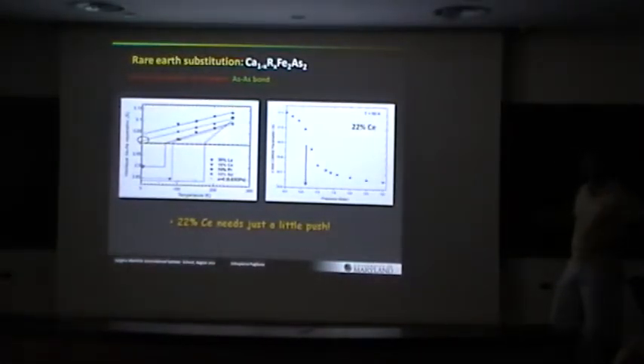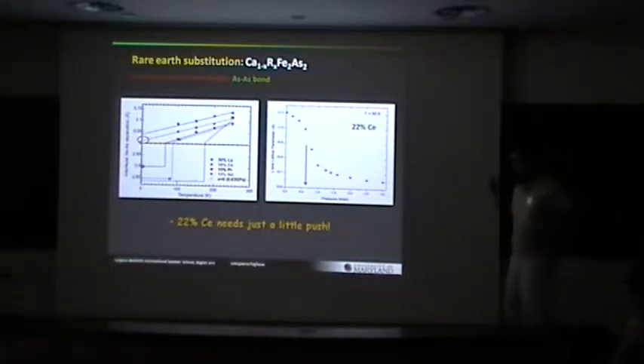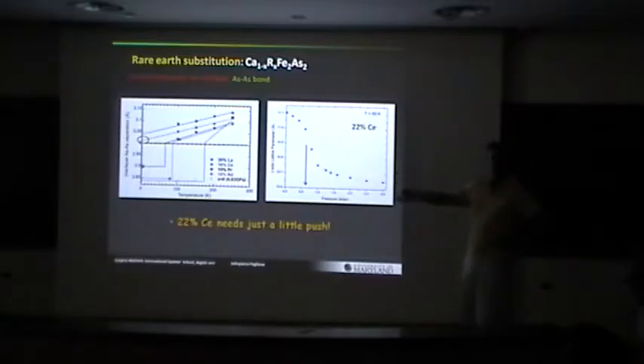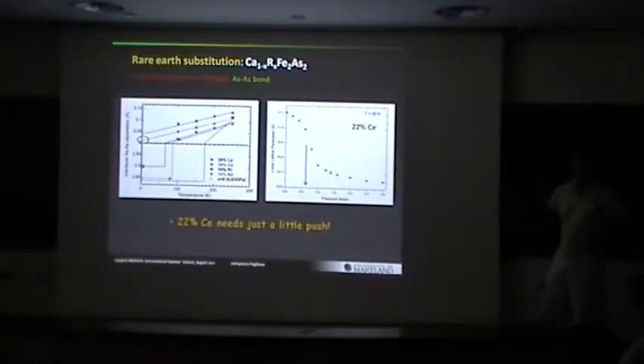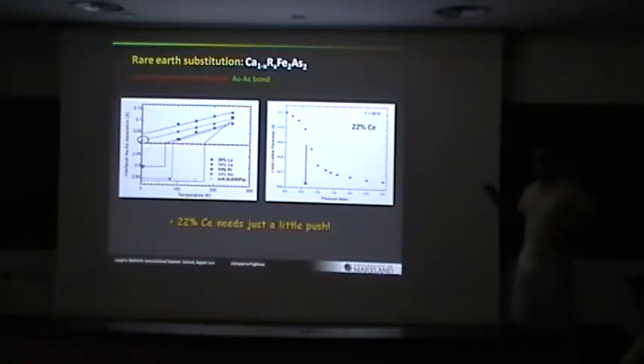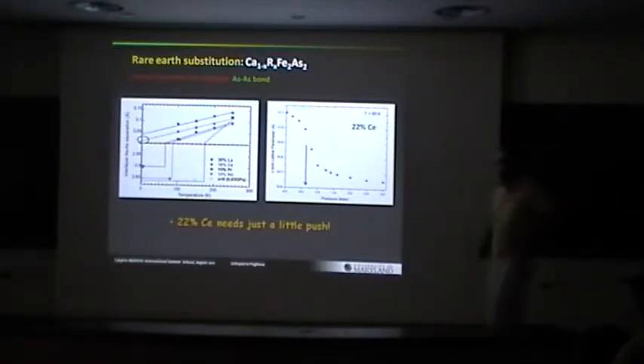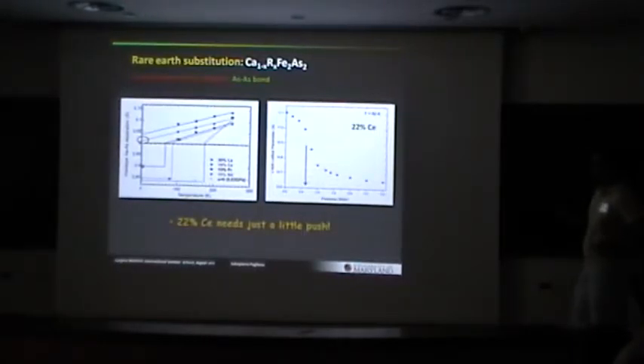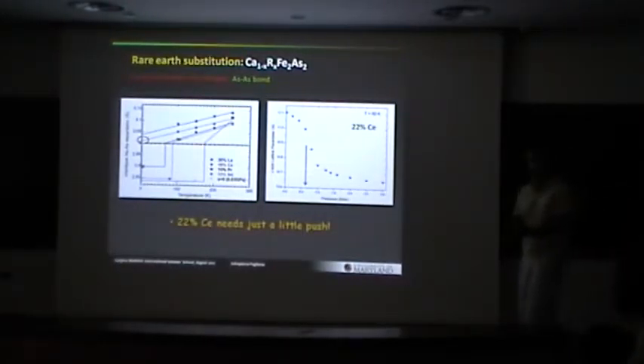Okay, and just to confirm this, if we take one of these samples, this is cerium, it's very close. We go to low temperature and we apply, this is now half a kilobar, so that's 10 times lower pressure than the calcium 122 pressure that's needed to induce the collapse. And here's the C-axis, it drops. So this is confirmation that you really need to just hit this 3 angstrom line to cause this collapse.